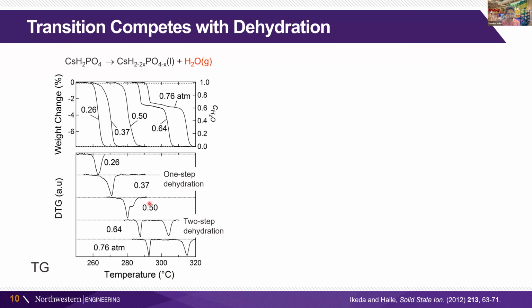And what you can see on the left is that we did a TG measurement, a thermogravimetric measurement, and we changed the steam partial pressure and looked at the mass loss. And there is indeed a mass loss, and you can suppress it by increasing the steam partial pressure. That's physical chemistry, absolutely what you would expect.